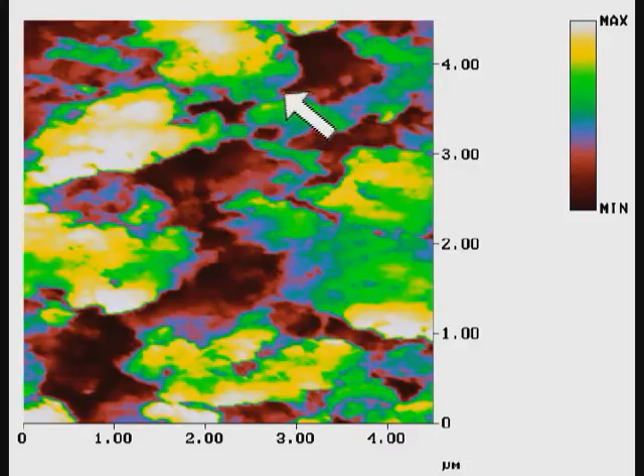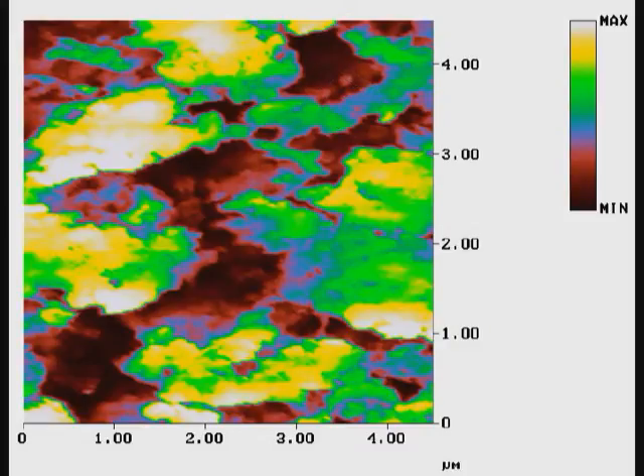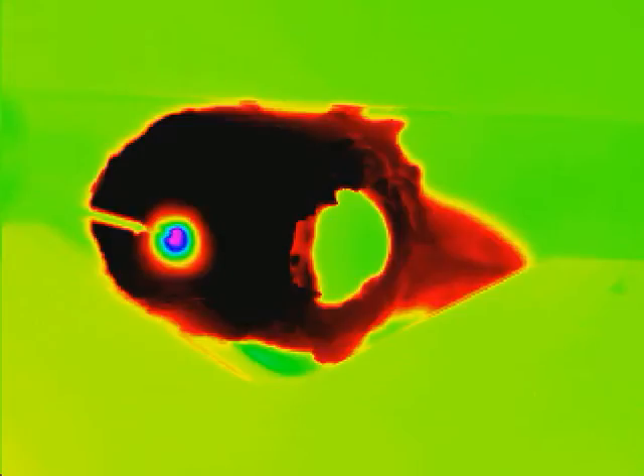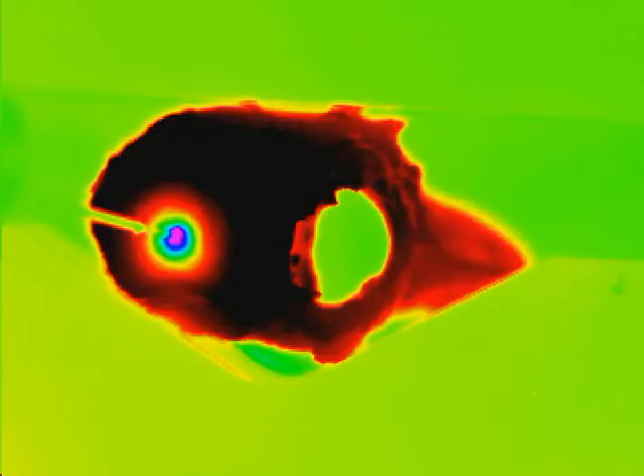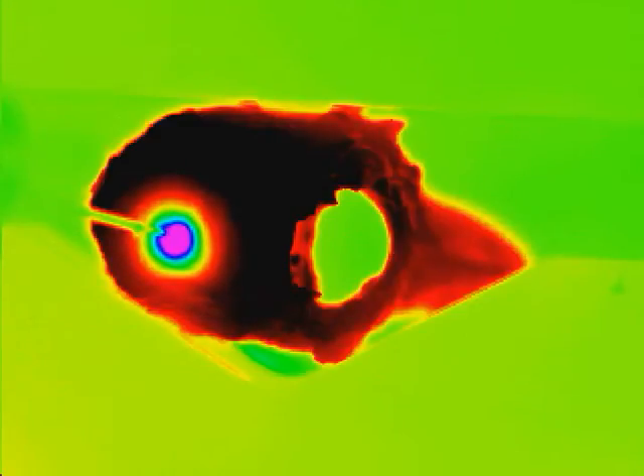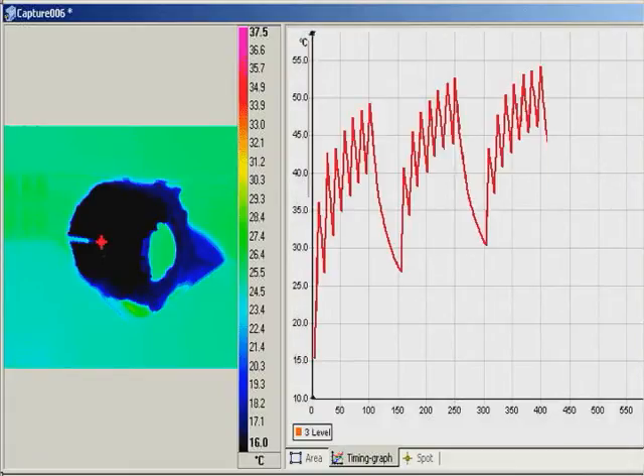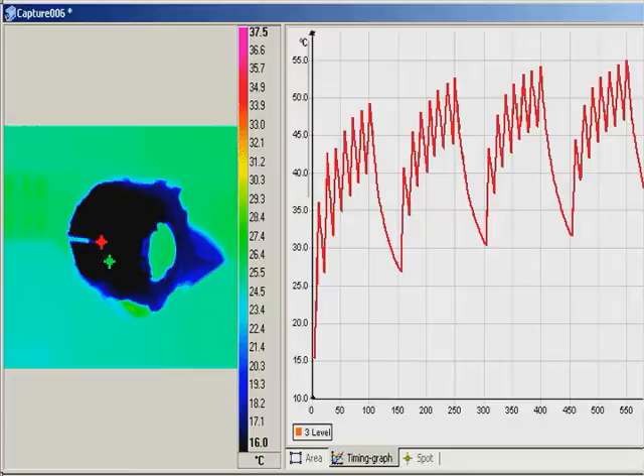These small bubbles provide a mechanical effect on the cartilaginous cells. The structure of laser-irradiated cartilage was studied with an atomic force microscope and formation of micropores in the matrix of cartilage was revealed. These laser-induced micropores are crucial for effective reconstruction of a disc. To reveal the peculiarities of the temperature fields inside the disc treated with modulated laser radiation, a high spatial and temporal resolution thermo-vision system was applied. The temporal modulation of the laser beam with a specific modulation frequency allows enhancing the opto-thermo-mechanical effects.